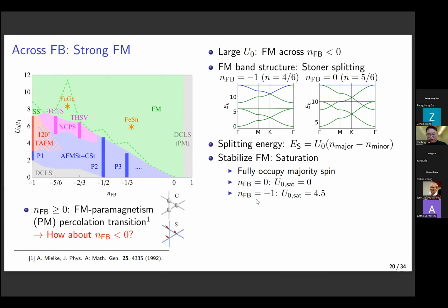However, if we go to the empty flatband, that is at this splitting, then we will see that we need to have a finite splitting to saturate the ferromagnetism, that is to push the majority spin bands below the minority spin Fermi level. And here our estimation will be around 4.5. So by doing this kind of estimation, we can see that the ferromagnetism is actually destabilized as we are pushing the filling below the half-filled flatband.